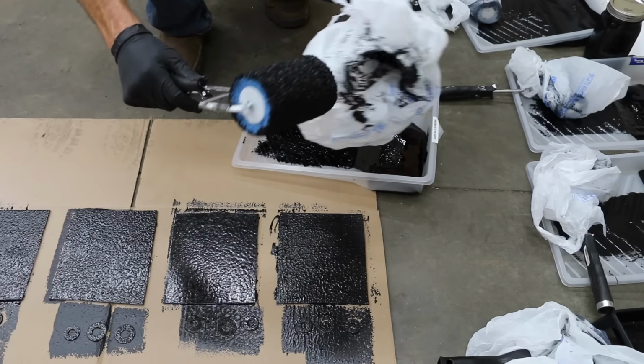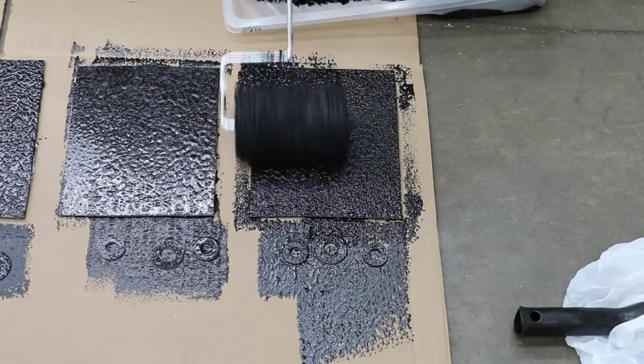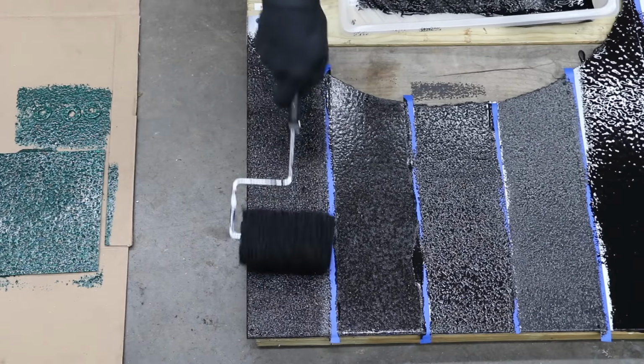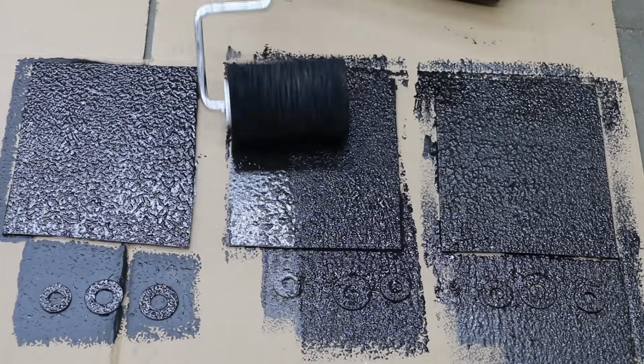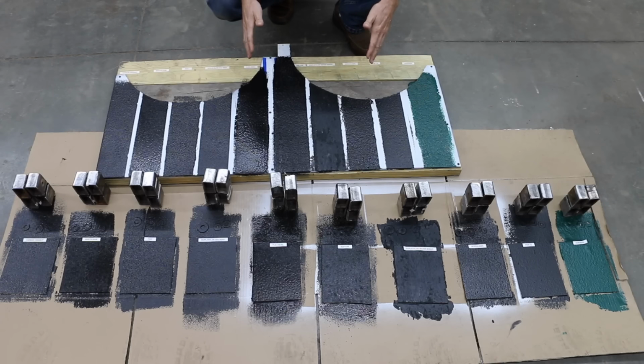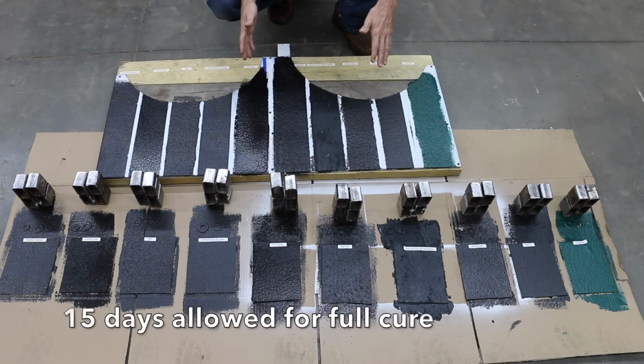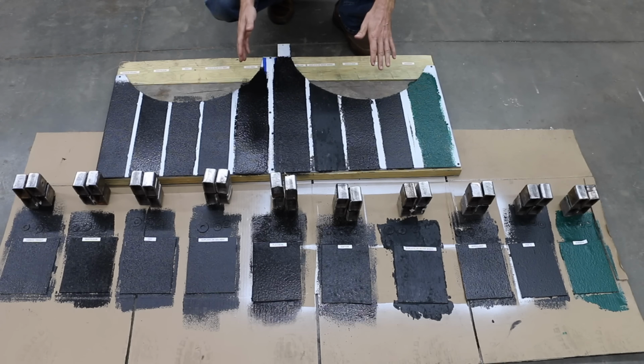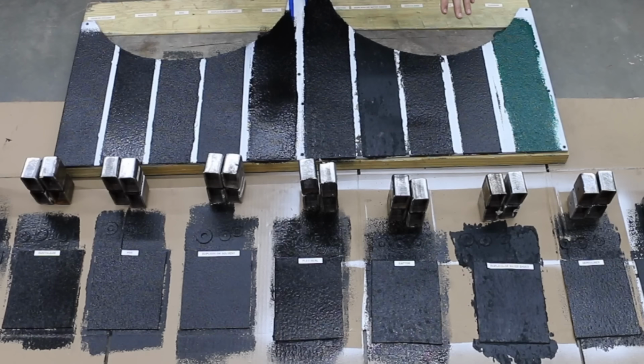All of the products received a second coat in accordance with manufacturer's instructions, which varied from under 1 hour to waiting 24 hours for a second coat for Flex Seal. To make sure all the products are fully cured, I waited over 2 weeks to begin the testing, and during the second week of curing, all these products were in a fully enclosed cargo trailer that reached temperatures of well over 100 degrees Fahrenheit, so each one of these products should be very well cured.